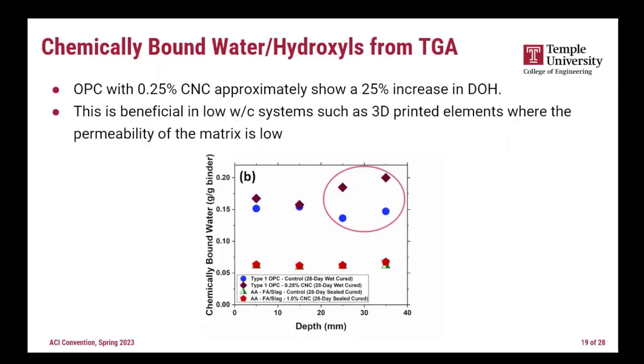The other interesting observation we had was the internal curing effect from the CNCs. When we look at the bound water over the depths of the samples, we notice that in the OPC system there's an increase in the degree of hydration. This can be really helpful in 3D printed systems, where we have lower permeability, right? The external curing effect is limited, or the depth is limited. So this is an interesting observation we had.